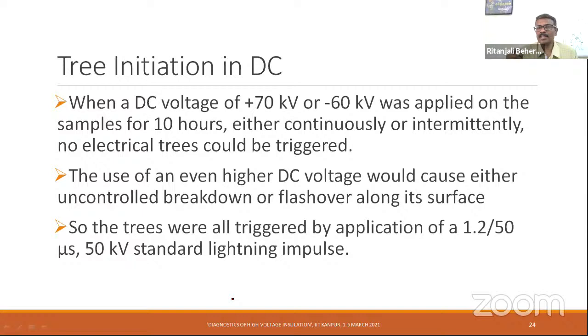However, the negative polarity also might help in initiating the tree in some cases. So some researchers have gone for applying an impulse voltage of 50 kV, and then initiate the first branch or initial few branches, because you cannot have control over how the tree will initiate when you apply impulse voltage. So, this is the tree initiation there.